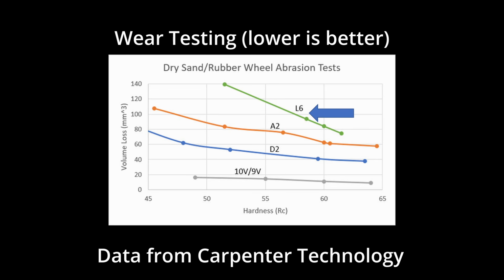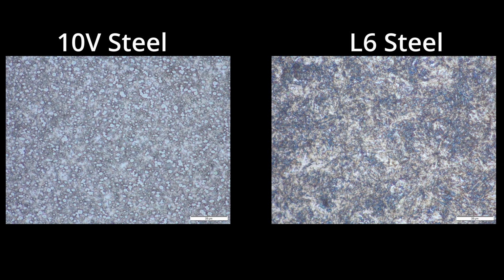Simple steels have relatively low wear resistance, and heat treating them to a high hardness only does so much. It has improved wear resistance at higher hardness, but a steel with a large amount of vanadium would still have vastly better wear resistance even at much lower hardness. The high vanadium steel has hard vanadium carbides that resist wear even if the steel matrix is not particularly high in hardness. The CATRA test is a common test of edge wear.